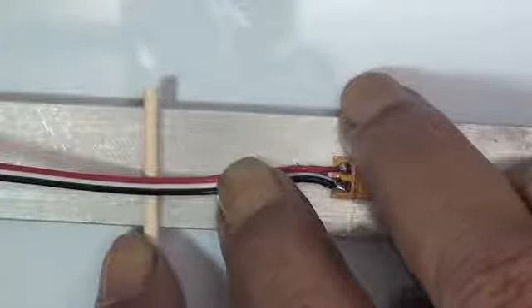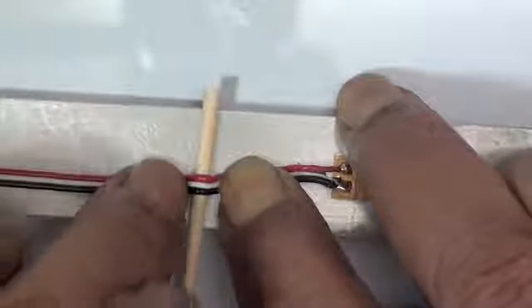So to prevent that from happening, I'm going to anchor this wire to the surface, but before that I'm going to put a strain relief loop in the wire by holding the wire down on the surface at one point, pushing down with a round wooden piece and pressing down the wire on the other side, which produces this loop over here. And this strain relief loop ensures that there's enough flexibility for the wire to stretch in case the beam goes into severe bending without snapping the strain gauge off the surface. Right, it just decouples the wire from the surface strain.